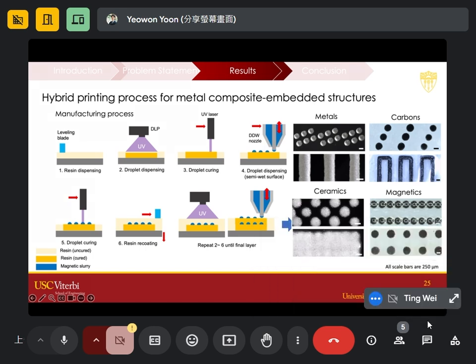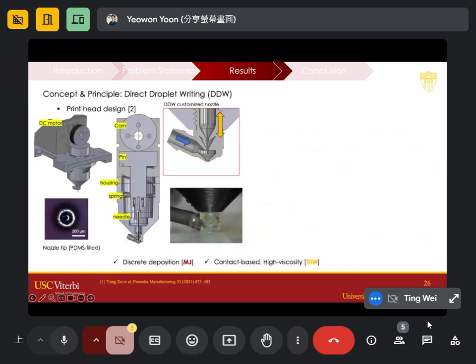We basically have a top-down printing process where we print one layer of the resin. Here it's very soft, and we have to use a secondary laser to make the surface extremely dry. Then a direct droplet nozzle comes in and prints the magnetic slurry. Once it's done, this goes down, the resin comes in, and this goes on and on to create a functional composite. Here we're able to print metals, carbon, a CNT mixture with the resin, ceramics, and also both soft and hard magnets.